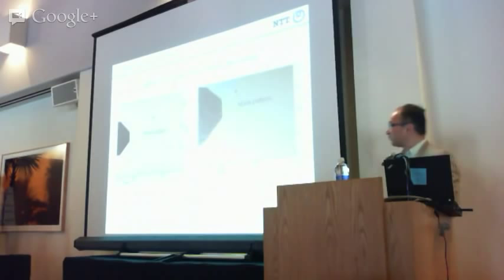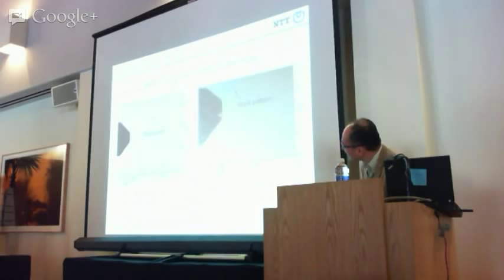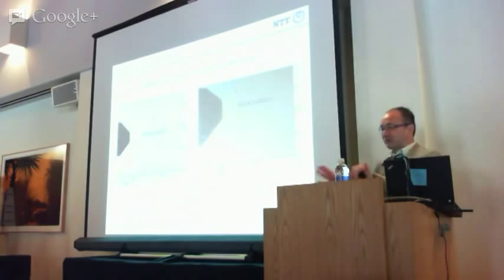Very important, but we cannot detail the difference between the diffusion to the active region and to the p-type region. But we can control a very low diffusion from the zinc channel diffusion. This is the mask for the n-type region, and between here is about one micron. This is the mask pattern for the zinc doping. So the diffusion of the zinc is less than 0.2 or 0.3 microns, so we can control the distance precisely. Next we will try to optimize the distance to the active quantum region.